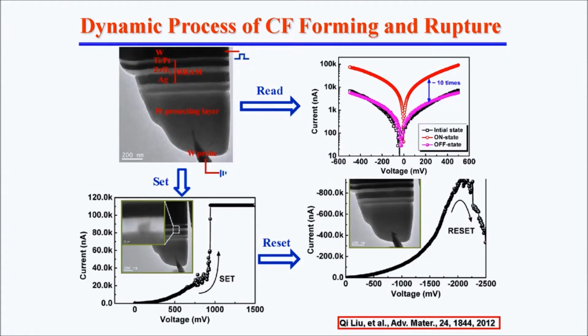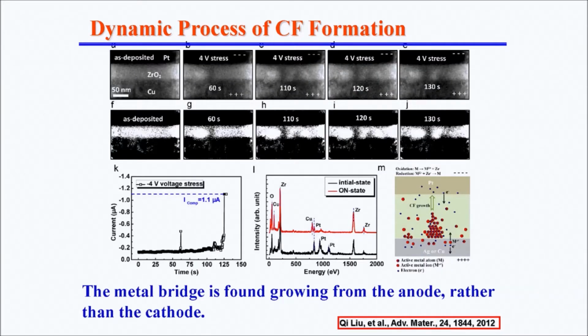Then when you apply stress slowly, the set process takes place. Meanwhile, we take the image here, and we can clearly see the filament forming here. Also for the opposite side, when we use the reset process, the current decreased. That means the formed filament disappeared. That's the first time we got the image of this dynamic process. This is a picture cut from video.